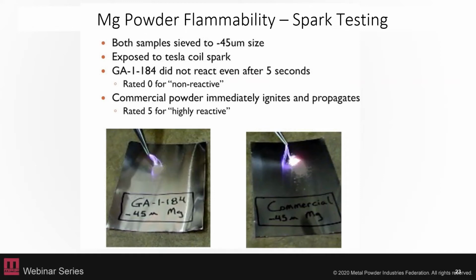So this could be something that you incorporate into your process, whether that's checking the powder as you're pulling it out of the machine, checking the flammability and how that has changed, and whether it's safe to handle normally, or whether something happened that means you now need to take extra safety precautions. And again, this test is pretty easy and quick to do, which is why we use it as a comparable scale for measuring our powders.